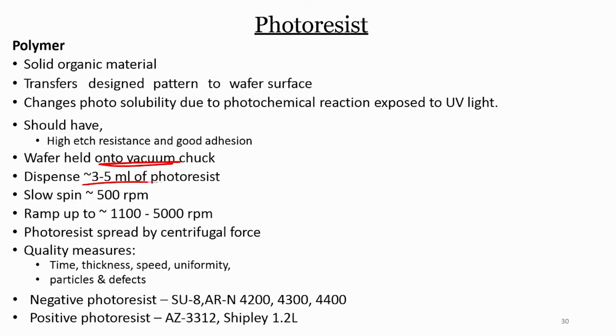and then dispense 3 to 5 ml of photoresist, then slow spin at 500 rpm followed by a higher rpm, or ramp up from 1100 to 5000 rpm. Photoresist is spread by centrifugal force. We will see the photoresist spin coating schematic in the following slides. And the quality measures are the thickness, the time, speed, uniformity, while particles and defects are something that we need to also understand, because the particles and defects will destroy your overall pattern.